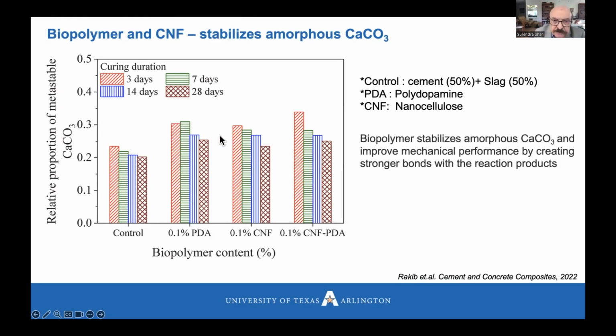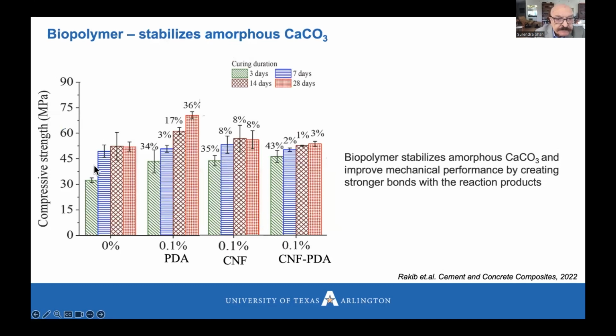It turns out you can also increase the amount of amorphous by adding nanocellulose fibers. And this increase is also mimicked in increasing compressive strength. For example, compressive strength after carbonation of control at different ages versus when you add 0.1% of polydopamine. And you can see we have increased compressive strength by 36%. So you have not only absorbed more CO2, but by controlling this, you have increased compressive strength